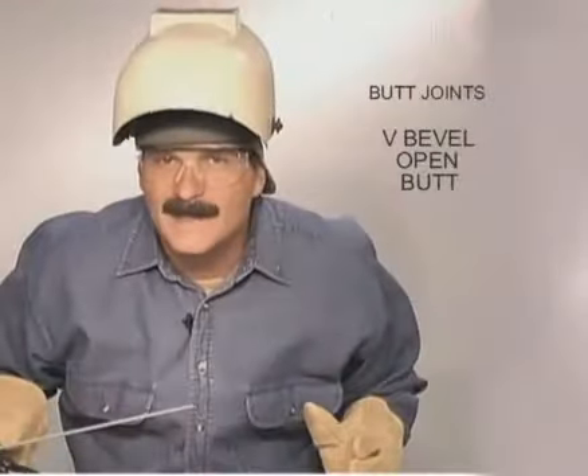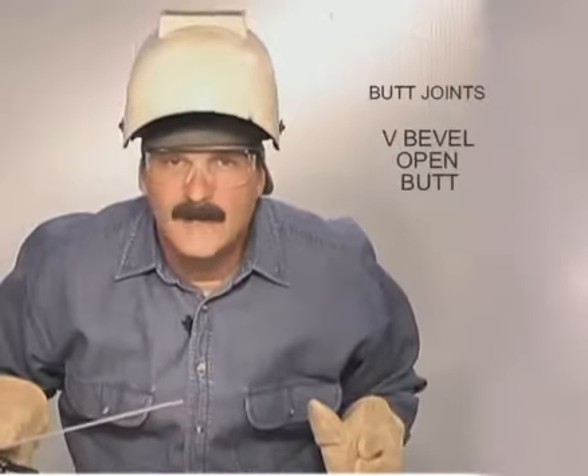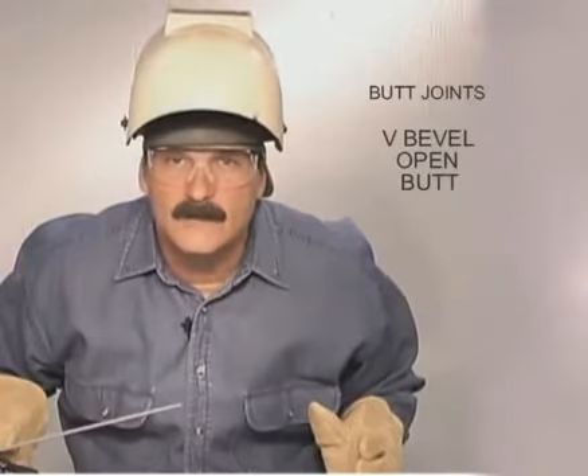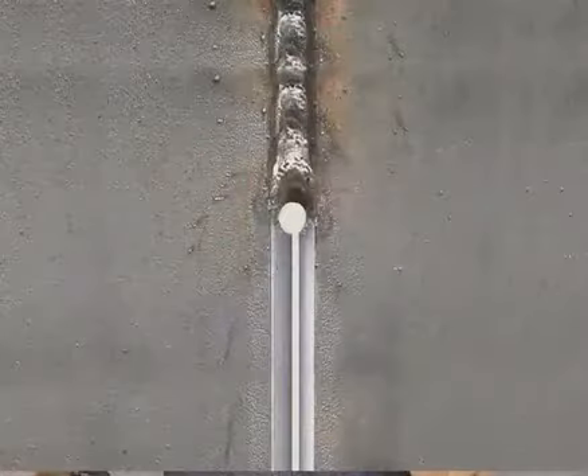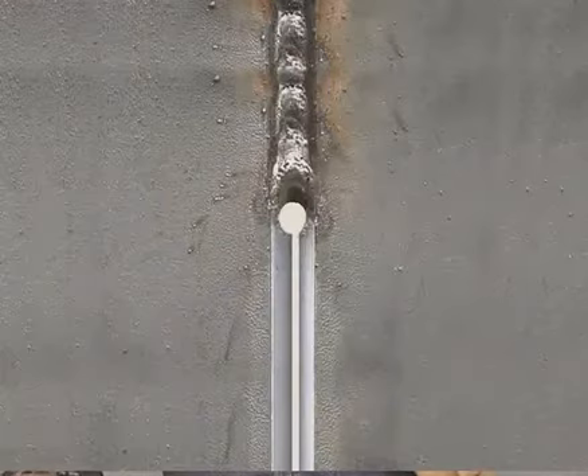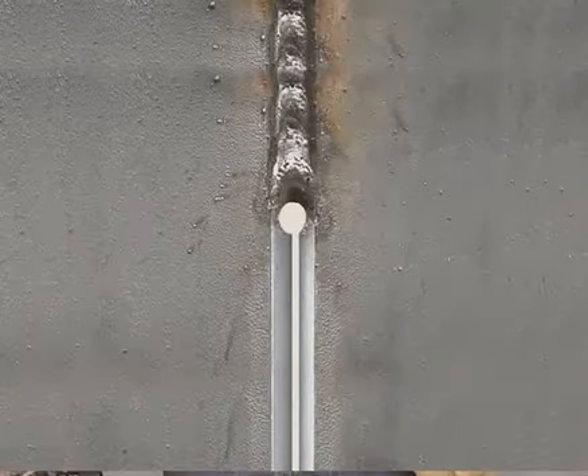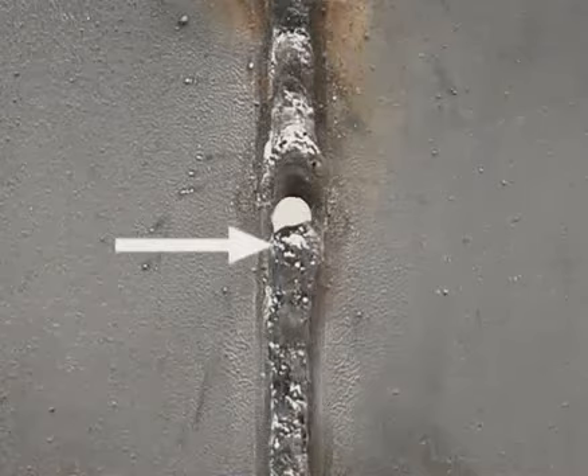If you're not getting all the way through, you will see filler metal squirting out behind the rod, back up in the bevel. Most of the light and sparks will be on the back side, and you're building weld on the back of the metal. You want the amperage relatively high, so try starting about the same place as you'd run flat. If you do open a hole, stop right away, pulling the rod back over the bead. Restart right at the edge and keep going.